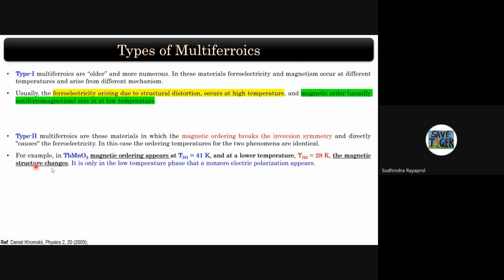But in type 2 multiferroics, magnetic order breaks the inversion symmetry, and because of that, you can have the ferroelectric and magnetic transition taking place at the same place, and it is the magnetic transition which causes the ferroelectricity in this type of multiferroics. One example of this is TbMnO3, where it can have two transitions, 41 and 28 Kelvin, but it is at 28 Kelvin that the magnetic structure changes, that is, the magnetic symmetry breaks, and there is an onset of the electric polarization.